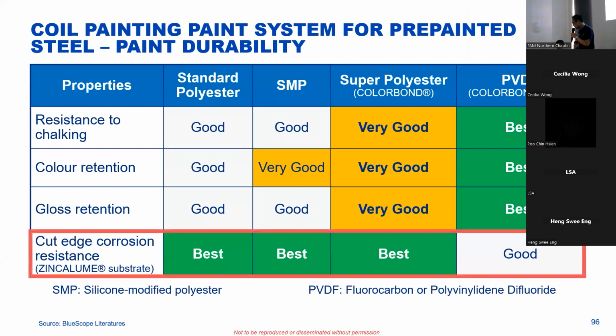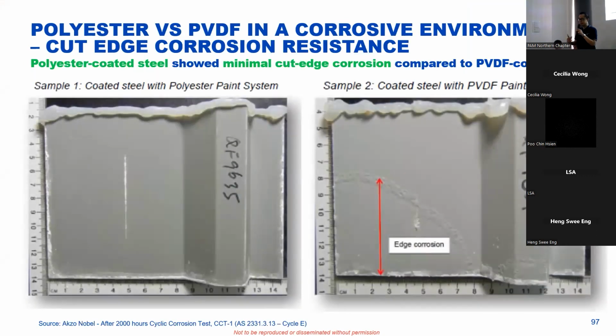Okay, the next part, I want to share about the cut edge corrosion. This is very important because from this diagram itself, we can see why the PVDF system will only give you good, meaning slightly inferior compared to the polyester. We have the reason why this can happen. Based on our lab study, if I put a sample inside a corrosion test chamber, this is a PVDF sample. You can see the cut edge corrosion happening. All the layer is already peeling, meaning corrosion has already happened. Compared to this, using the polyester system, there are no peeling signs observed on the sample.